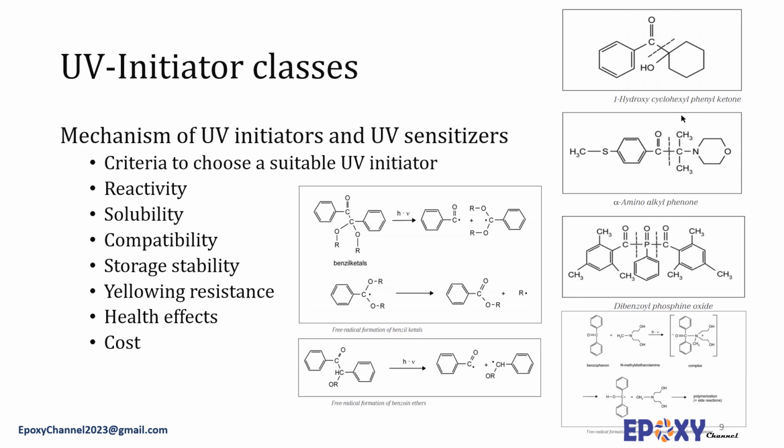Alpha-hydroxyalkyl phenones also have high reactivity. Liquid derivatives with aliphatic side chains are heat resistant and are more suitable for solvent-free paints. 1-hydroxycyclohexylphenyl ketone is an odorless solid and has excellent storage stability. The alpha-aminoalkyl phenones, with structures comparable to those of alpha-hydroxyalkyl phenones, are suitable for pigmented UV systems. However, they have a more yellowing tendency.